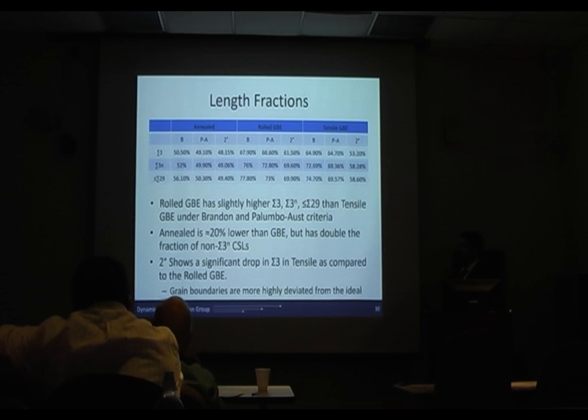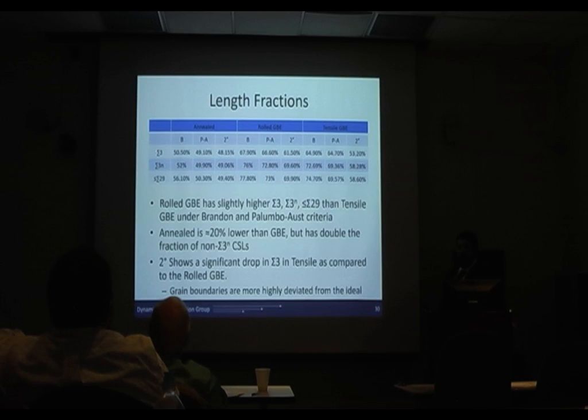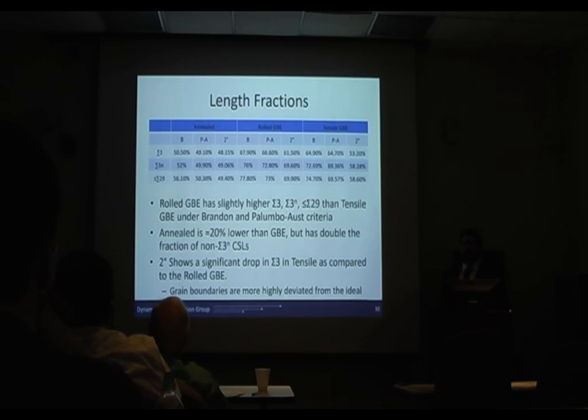However, there's several different ways to classify that. The most traditional is the Brandon, that's represented here by the B. And then there's also the Palumbo-Aust criterion, which is a little bit tighter, and that's been shown to track a little bit better with corrosion performance. Then there's also just a flat 2-degree cutoff. And that's actually much tighter for sigma 3s and a little bit looser for the higher order sigma grain boundaries. And what we found was that the rolled GBE has slightly higher content than the tensile GBE, and the annealed is about 20% lower in length fraction compared to the GBE.